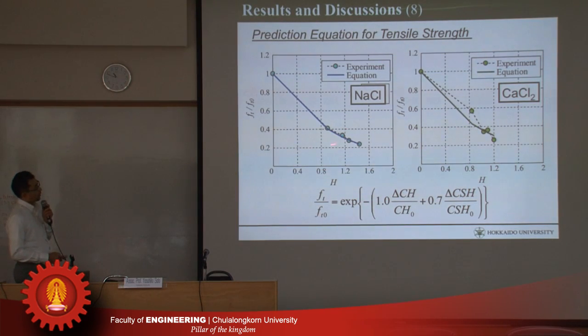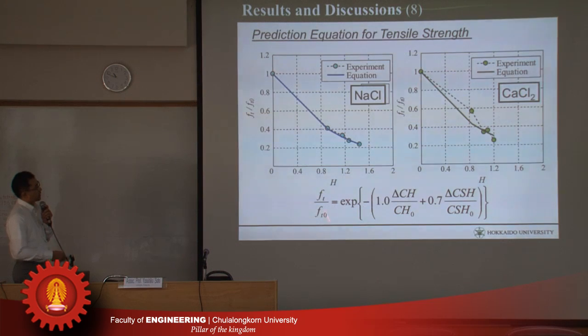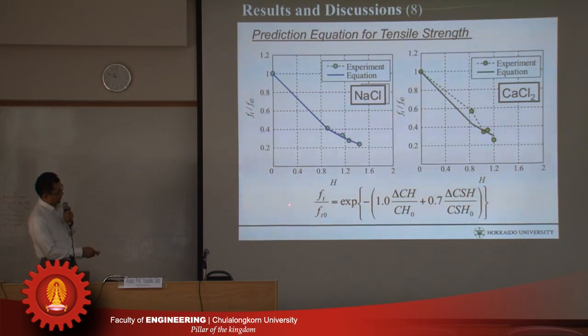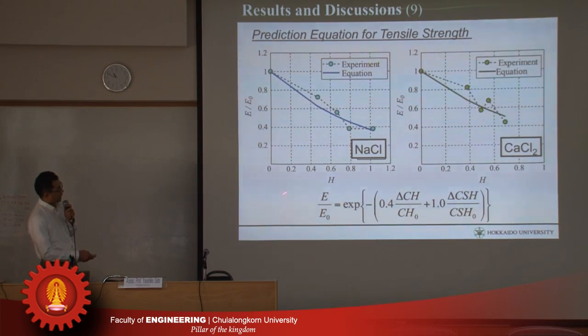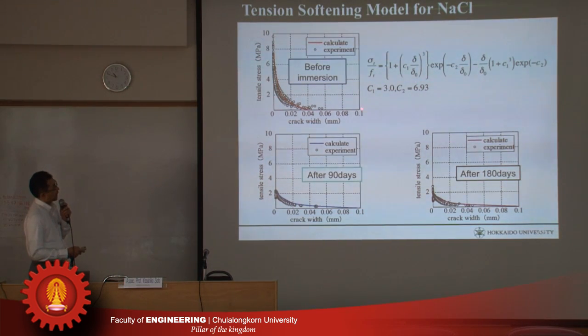This is the relationship between the strength change and the amount of hydrate — combining the parameters with CH and CSH. Using this kind of relationships and findings, we can find equations which represent the strength change, Young's modulus change, and so on. Using the current equation — the FEM — we introduce the strength or fracture analysis, and we can draw the softening curve.